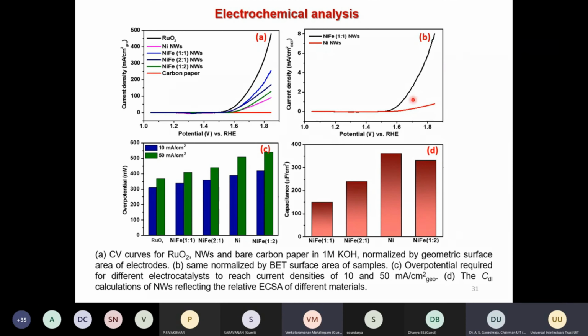So here I can compare how, without iron and with iron, there is a decrease in the overpotential for the oxygen evolution reaction. This is the overpotential graph for various samples at different current densities. As I said, this 10 mark is generally taken as 10 milliampere per centimeter square, but it is not really very appropriate, I should say. So we have also done 50 milliamps, to see how much extra overpotential is needed to reach 50 milliamp per centimeter square.